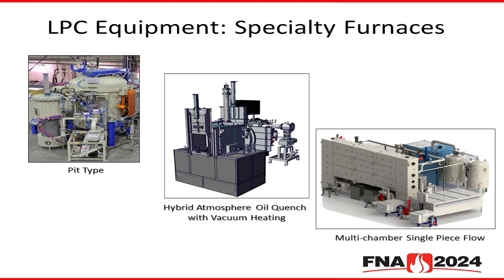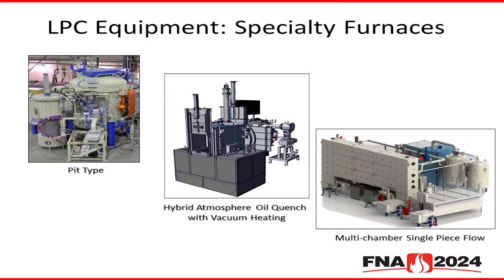Then there's also a hybrid atmosphere oil quench with vacuum heating chamber solution. Here it's a combination of a standard IQ style quench chamber mixed with a vacuum heating chamber. So it works a lot like the two-chamber vacuum oil quench that we discussed earlier, except the fact that this chamber does not operate under vacuum, but rather atmospheric conditions, using nitrogen, of course. But again, the advantage here is that you get the vacuum heating option and can conduct low pressure carburizing or LPC in that chamber.